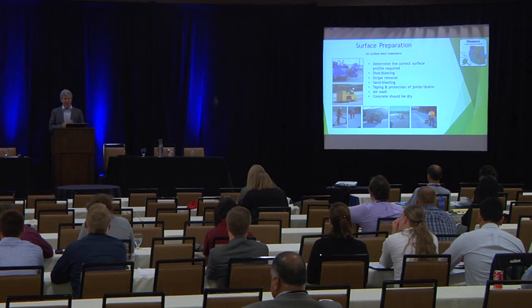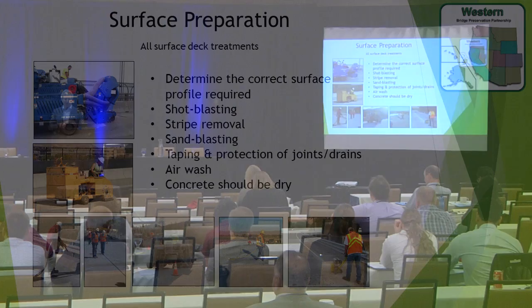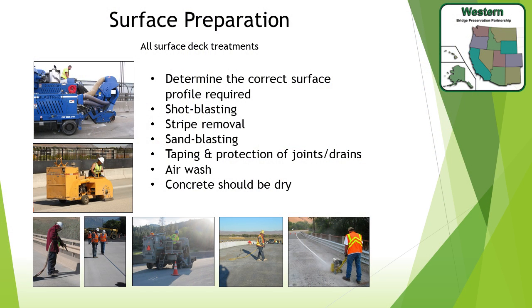Taping of joints and drains is important. Air washing is important — even after shot blasting, you want to get a 175-180 CFM compressor with an air lance, get close, and blow out all the dirt, dust, and debris off that deck. The concrete should be dry. If there are concerns, you can use a torch to bring moisture to the surface to check, or use the ASTM test method of taping down two-foot-square plastic polyfilm — typically a 16-hour test, but two hours can give enough information. The ICRI profiles are referenced in a lot of specifications, but most people don't know what they look like or what they mean. For an inspector to have that conversation with the surface prep contractor without having the physical profile chips is meaningless — a number 10 being most aggressive, number one a very light sandblasting.